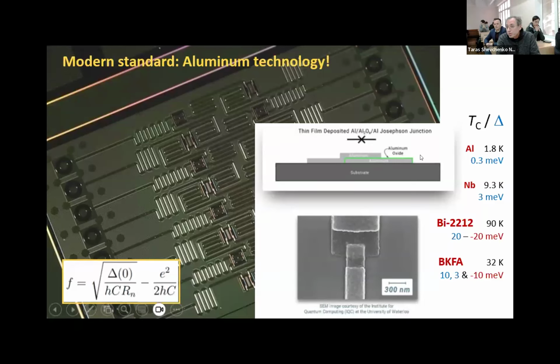And actually, this decoherence problem could maybe be solved just by switching to another material, because here we use, not we, but all the people now, the modern standard, aluminum technology. It is based on aluminum superconductors because it's very technological. It's easy to make these Josephson contacts. But the superconducting gap of aluminum is very low. It is 0.3 milli-electron volts.